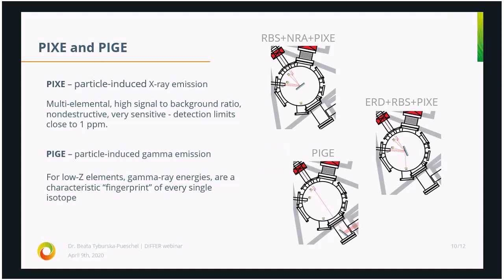So you can detect multiple elements at the same time. This technique has a very high signal to background ratio. It's non-destructive, it's very sensitive, so you can even go down to 1 ppm sensitivity when detecting your elements. We have this technique available in our IBA chamber, so you can, for example, perform RBS, NRA, and PIXE together, or you can perform ERD, RBS and PIXE together.